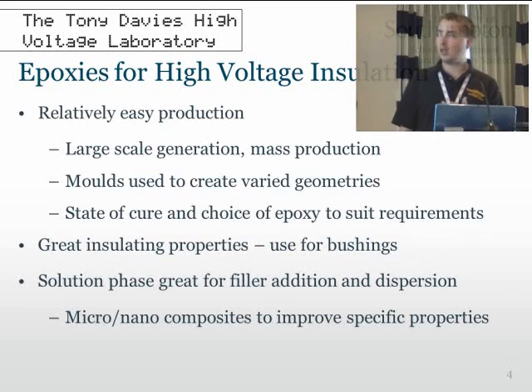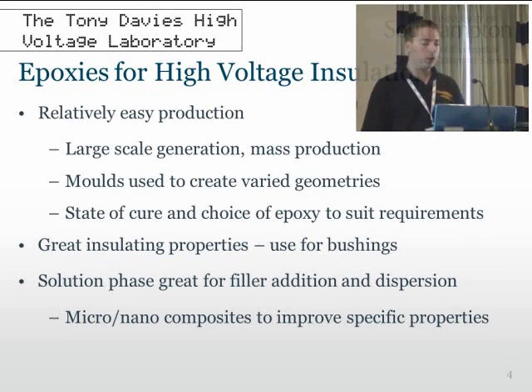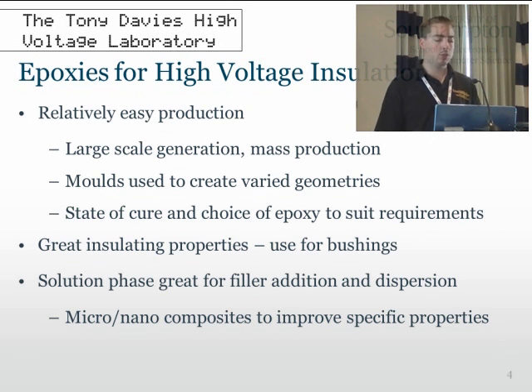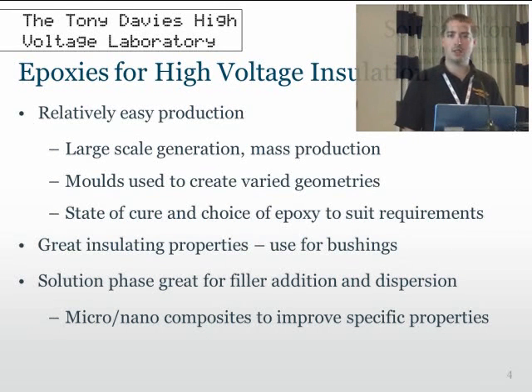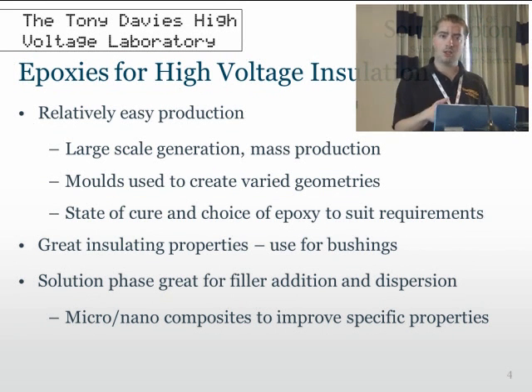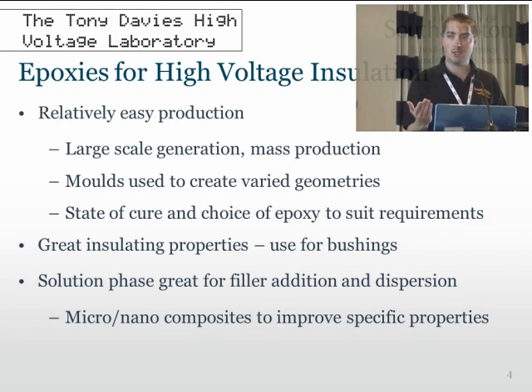Okay, so in particular for high voltage, one of the main reasons that epoxy is so tempting to use is the relatively easy production. You can store these two stable liquids and combine them when needed, which allows large-scale mass production. You can use moulds to create almost any geometry of samples, as well as final products. And also the state of cure and the choice of which epoxy you use with which hardening agent give you the material properties that you desire.